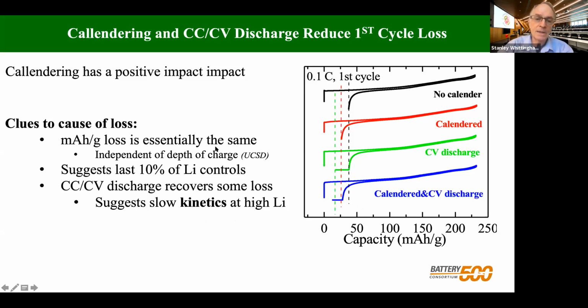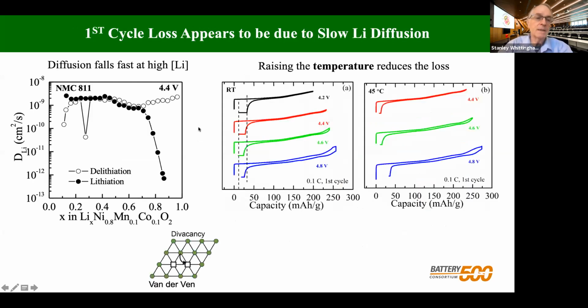And our colleagues at San Diego charged these to different amounts, like 20%, 30%, 40%, 50%. And this first cycle loss was exactly the same, which suggests that it's the last 10% of the lithium that does not easily go in. So let's just look at what we in fact did. We then measured the diffusion coefficient of the lithium in these materials. The black circles here are in diffusion. You can see this is quite high to begin with, about 10 to the -9. Once you get above about 80% lithium, it falls off by about 4 orders of magnitude. So, a tremendous fall off here.